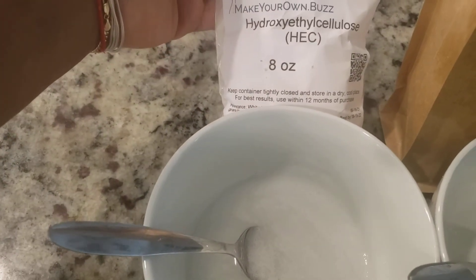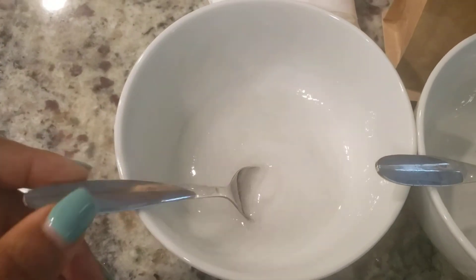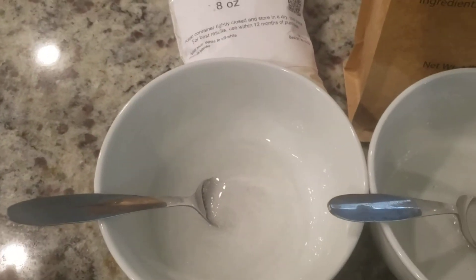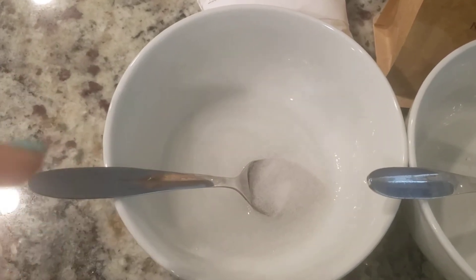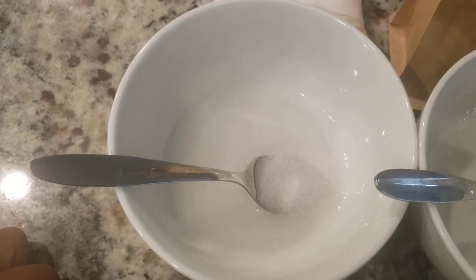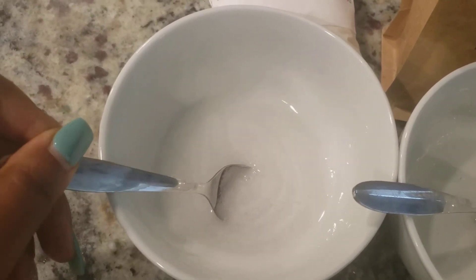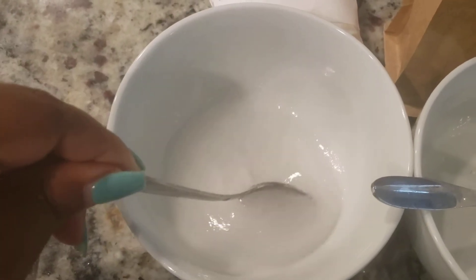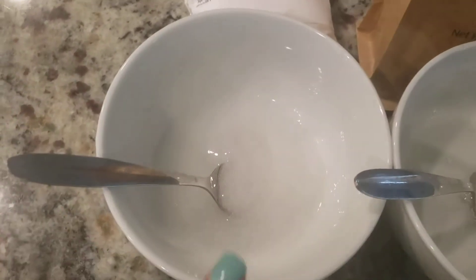For the hydroxyethylcellulose, the powder in the water just literally sat for so long that I almost gave up. I had it sitting for at least 30 minutes to an hour and it still just had powder at the bottom, so I let it sit overnight. When I came back down this morning, the water was more or less sitting on top, and it had a really thick gel — almost like hydrated raw gelatin. So I used my immersion blender for a few seconds to disperse it evenly throughout the water.